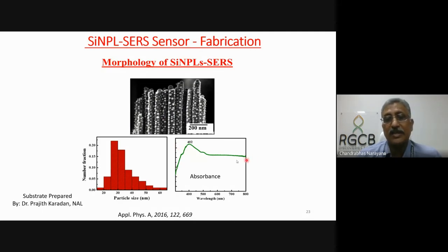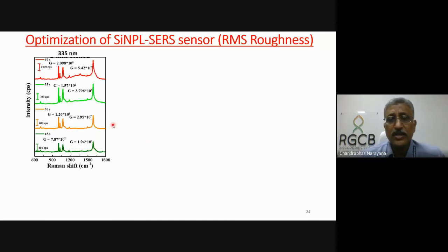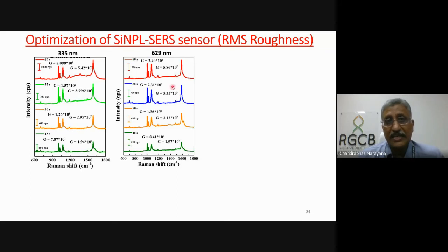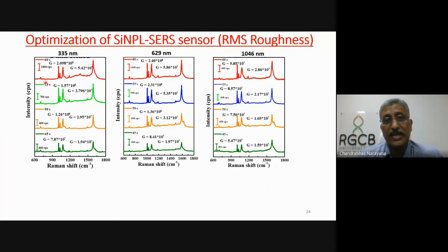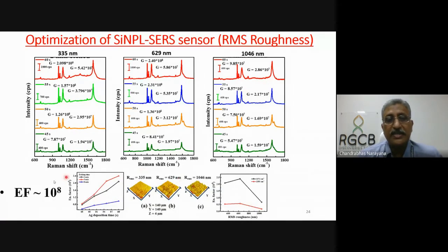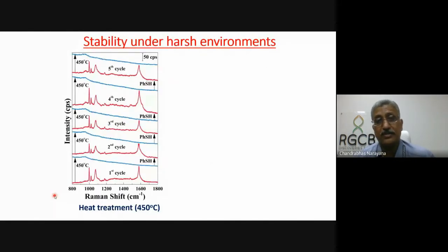Surface plasmon was actually active in all ranges of the wavelength of light. This was very interesting for us, because that means we do not have any dependence on a particular wavelength of light we need to work with. Now you can see we use UV light, red light, and infrared light. So the enhancement is more or less consistent, roughly around 10 to the power of 8, which is good enough for most biological systems.